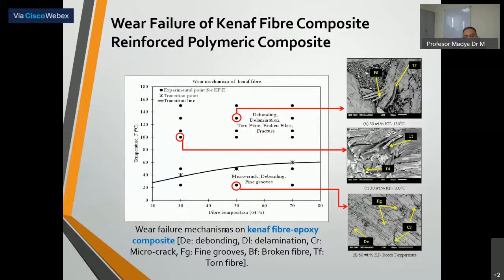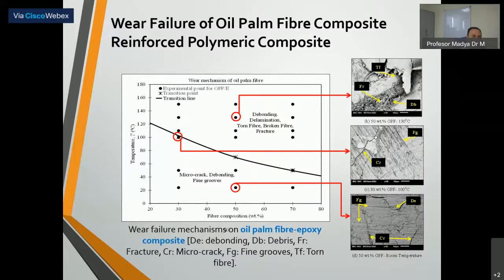Okay, this is the failure mode of the kenaf fiber. We can see that there is some debonding, some delamination, and then the torn fiber, broken fiber, and also fracture of the fiber. In the mild wear region, we can see only micro cracks and also fine grooves, because of the gouging. Okay, this is the oil palm fiber reinforced composite wear failure.